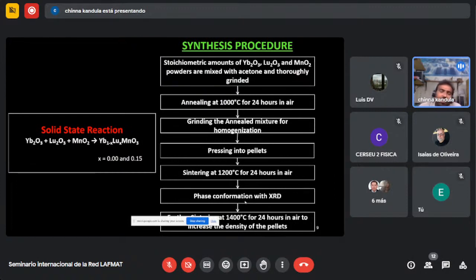The stoichiometric amounts of ytterbium oxide, lutetium oxide, and manganese oxide are my initial precursor chemicals. They are taken in oxide form, and the purity is very high because we purchased these oxides from Sigma Aldrich with 99.99% purity. In solid state synthesis, to get a good quality sample, purity is a must. Initially these samples are weighed according to the stoichiometric ratio. After that, they are heated at 1000 degrees centigrade for 24 hours in air atmosphere. After that, there are several grinding processes.